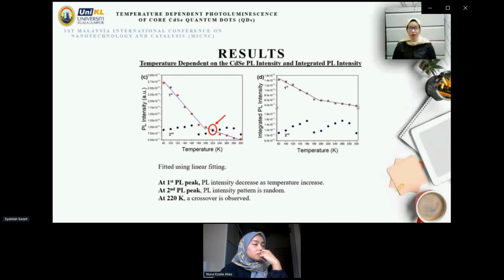For the second peak, the PL intensity is inconsistent, and the reduction of PL intensity at low temperature is a result of carrier trapping in defect states, where at low temperature thermalization can occur. These trapped states are commonly known as the PL spectrum's low energy shoulder.